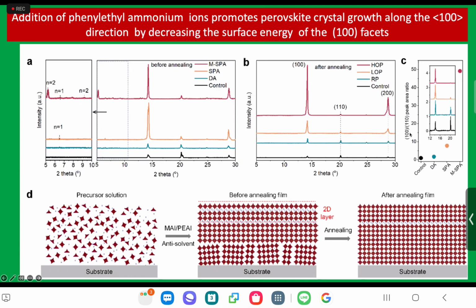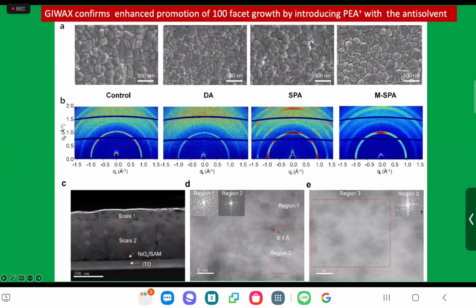And so you see if you look at the right side, the critical thing is seen here. That's a ratio of 100 to 110 peaks in the XRD. You can see this goes from 1 to 50. That's really stunning. By just adding this in the antisolvent. And so what you do is you get a real nice cubic, and that is also confirmed by the GIWAXS.